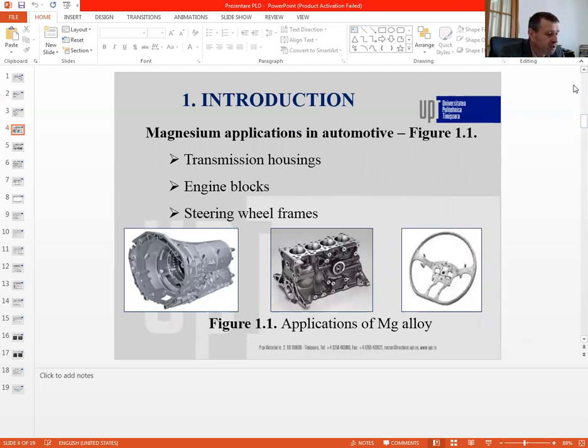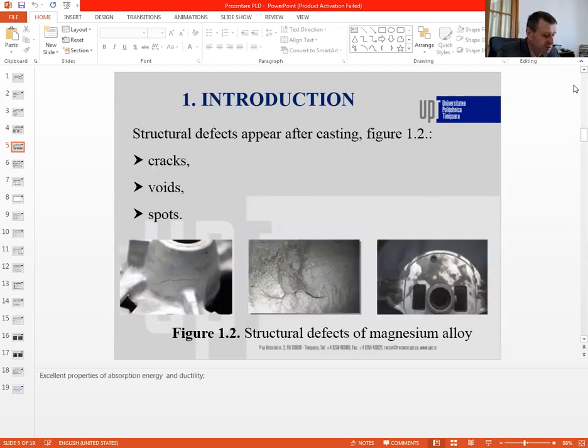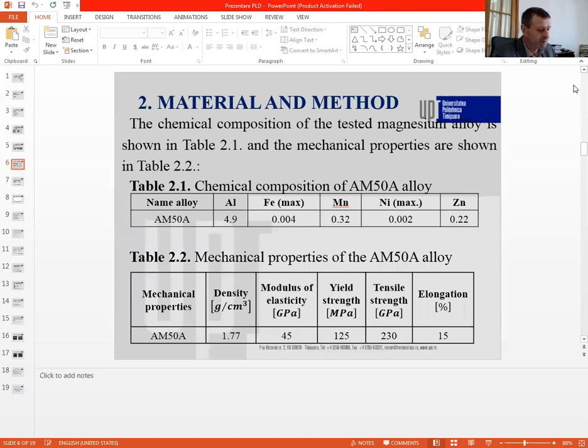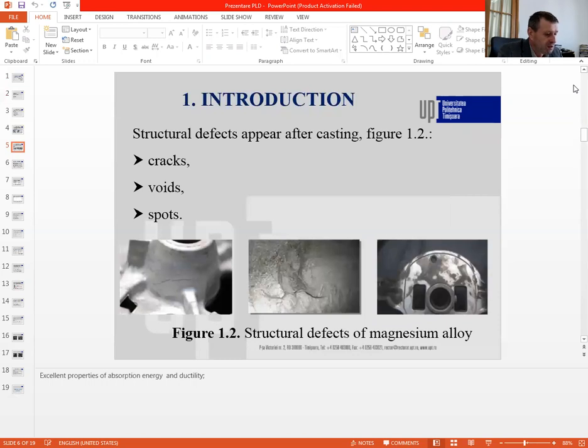In automotive, magnesium alloys are used in applications such as transmission housings, engine blocks, steering wheel frames, and others. Structural defects are the most difficult to identify because they are found inside the material and require special attention. The structure of magnesium alloy has a high density of casting defects that can occur as cracks, voids, spots, and others. They can be identified by non-destructive testing using X-ray equipment and penetrating liquids.